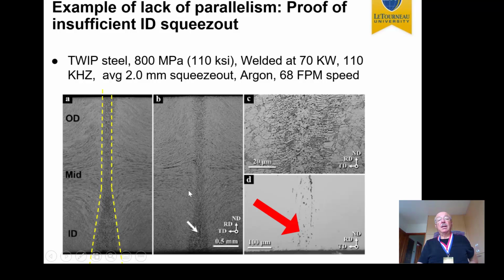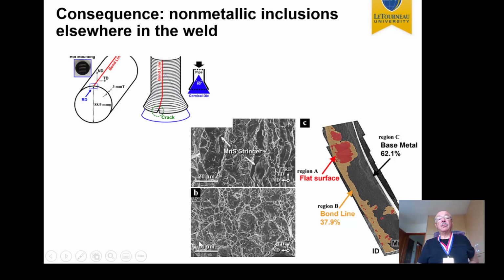So the fact that this bond line is wide, that's only one thing. In my opinion, it's too wide. But again, they did not squeeze out properly at the ID, and they have lines of inclusions. As a consequence, when they did a flare test, they actually opened those inclusions up, and lo and behold, they were lack of bonds. It's very little bonding. It was oxide inclusions at the interface. So the bond line parallelism is really important.